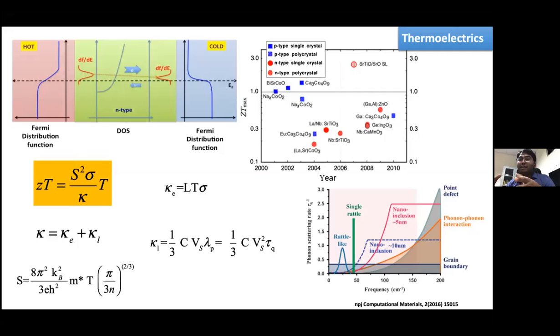Seebeck effect: when you have a temperature gradient in a sample, some of the carriers on the hot side will excite to a higher energy level because of the thermal energy that you have. You can see the hot side here. So there will be excess carriers on one side compared to the colder side. This difference in the carrier density basically drives a diffusion current from higher concentration to lower concentration. And when these carriers go to the other side, let's say many electrons have traveled from the hot to the colder side, this becomes negative and this becomes positive.